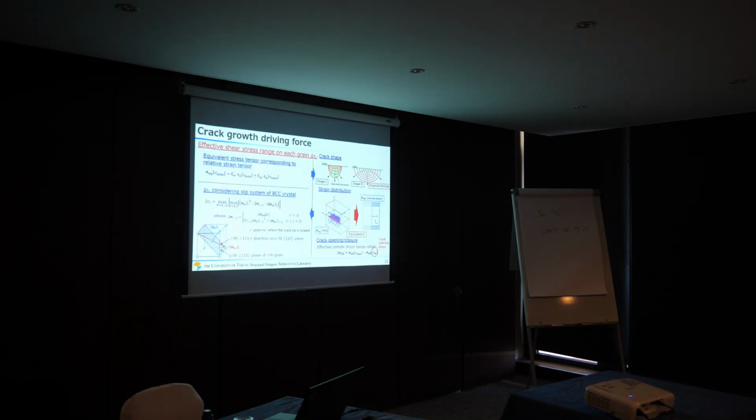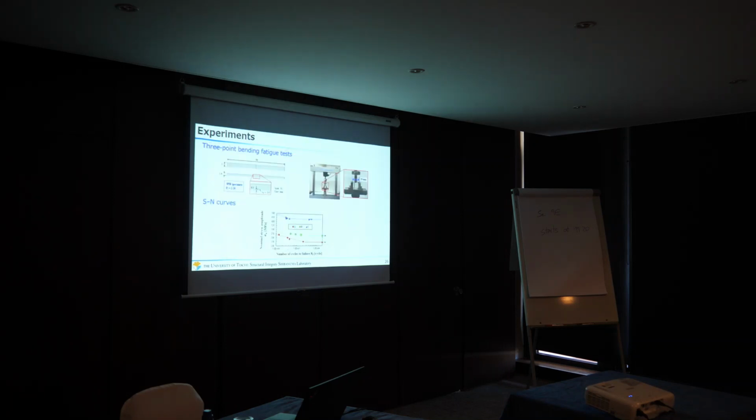Okay, thank you for your question. Actually, you can see our specimen has a very thin thickness, only 1.9 millimeter. So our model only considers, maybe you can say, a short crack. But in our recent research work, we also validated our model for a long crack. We tested a specimen with 6 millimeter thickness, and our model can also successfully predict the fatigue life and limits. But in this presentation, I only show the small specimen.